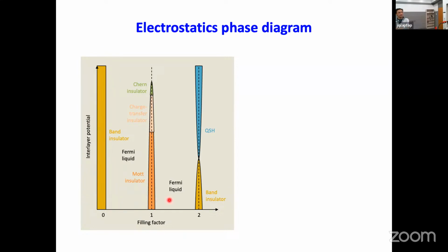And the x-axis is the filling factor, which is also continuously tunable. I told you about the topological phase transition from a band insulator to a quantum spin Hall insulator at filling factor equal to 2. It happens around here. And I also told you about how we introduce a topological phase transition from a charge transfer insulator to a Chern insulator along filling 1.